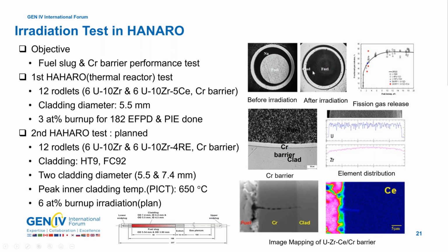This shows the PIE result of the Hanaro, before and after irradiation, at about 3% burnup. This red point shows the fission gas release state. It's low burnup, so there is some scattering in the measured data. This shows the chromium barrier, and it works well. The barrier was intact and the thickness was uniform, but some cracks were found in the cladding here. So we worked to prevent this cracking.